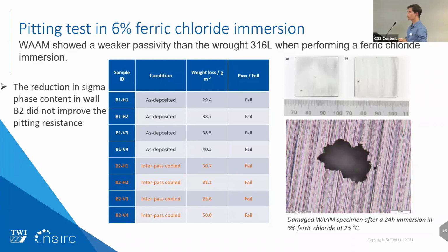So this is a bit in contradiction with what we have previously seen. When performing the potentiodynamic test and the CPT test, we had higher CPT and higher pitting potential for the WAAM material when compared to a wrought material. And here we can see the inverse phenomenon happening, where the WAAM material performs poorly compared to a wrought.